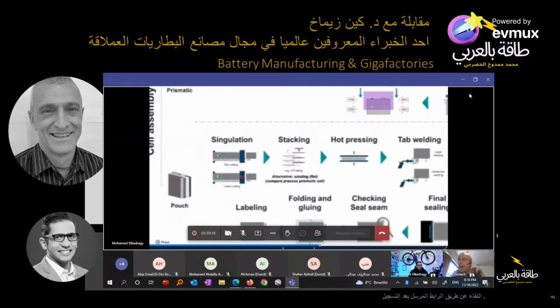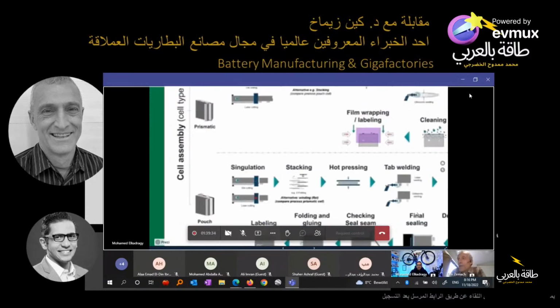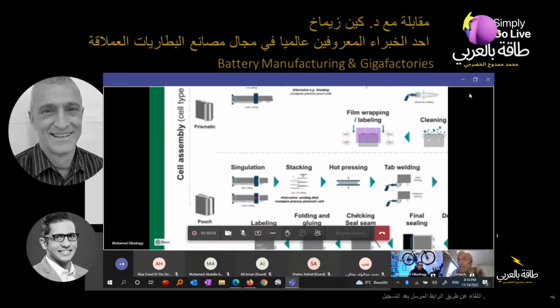You go watch some of those videos and watch how fast those sheets get stacked. And now I'm going to tell you that on a not great quality cell, the anode might be 2 millimeters wider than the cathode. So you have maybe plus or minus 0.5 millimeter of alignment on all 4 sides, corner to corner. And you watch these stacking videos, and it's stacking these things at sheets per second with sub-millimeter alignment accuracy. Now, it's not done by a person, it's done by automated machinery. But if it gets it wrong, how do you know? Because that's a safety issue. I guess you will know when the cell explodes.